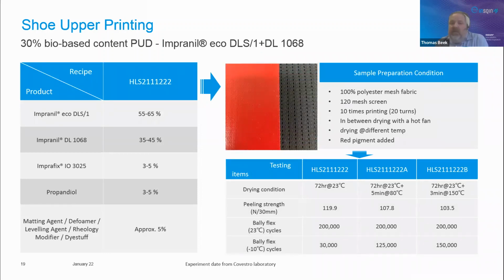This is a shoe upper recipe with a 30% bio-based content. We ran these trials with a recipe that was a combination of the bio-based material and a standard PUD material. We used again the Impranil Eco DLS/1 with the Impranil DL1068, which is a polyester-based PUD with nearly 50% MBC. Like before, we used Imprafix IO 3025, again with propanediol and some matting agents, leveling agents, rheology modifier, and also dyestuff. The printing was done on a black polyester mesh with a 120 mesh screen, and like before, again with 10 times printing.